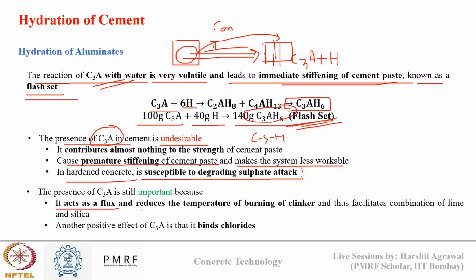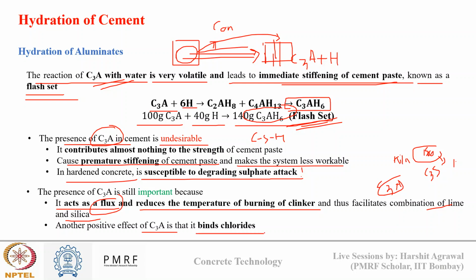Because it acts as a flux and reduces the temperature for burning of clinker. When we talk about clinker production in the kiln phase, the presence of C3A reduces the temperature required to form C3S, that 1500-degree mark. If there is no C3A, we would need to increase this temperature to maybe 1700 or 1800 degrees Celsius to combine lime and silica. So that's why we say C3A acts as a flux. Another positive point of C3A is that it binds chlorides. Over time in this course, we'll understand that chlorides are the major source of corrosion in reinforced concrete. C3A, if present, has the ability to bind chlorides when they ingress through concrete. So C3A is again important to us.